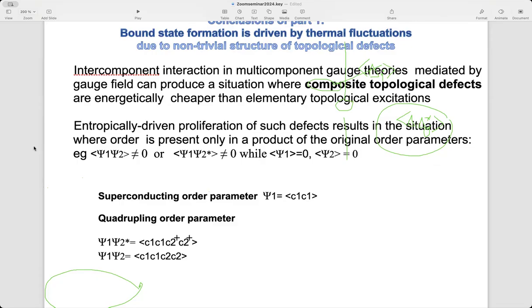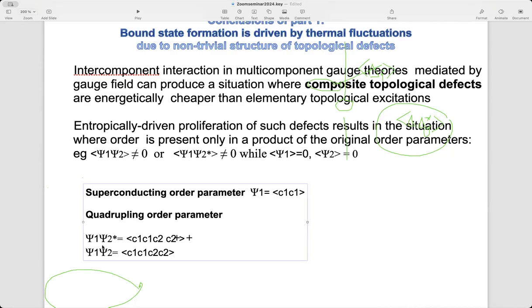In terms of symmetries, it means that if you proliferate composite topological defects first without proliferating individual ones, you basically partially restore the symmetry, you still retain non-trivial higher order correlations in the system. And these types of correlations could be either, let's say, this metallic superfluid, or a charge-4e superconductor, which is another order parameter composed of four fermions, or a counterflow superfluid, where only the relative motion of pairs of fermions is dissipationless.